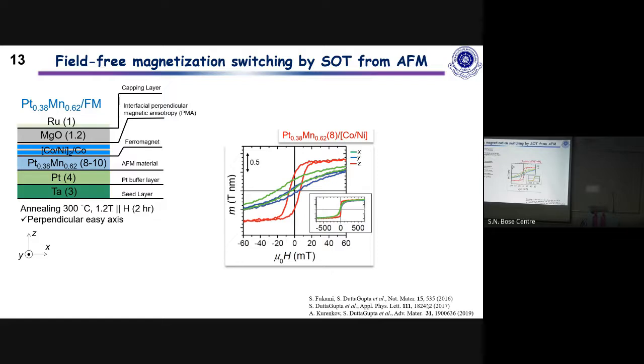If it is polycrystalline, how do I understand the difference between X and Y? It's a little bit of difference. No, this X and Y is just based on the convention of the samples. Still, you see a difference, actually this green curve that you see, this exchange bias that we see, is around the direction where we have annealed the sample. The magnetic field that was applied during annealing was along this particular direction.